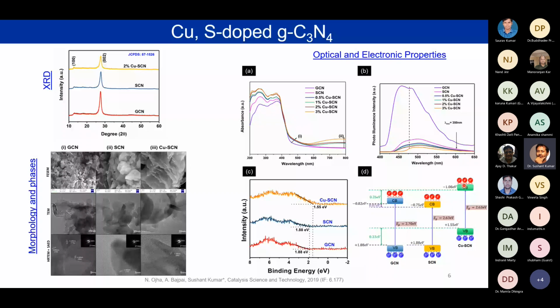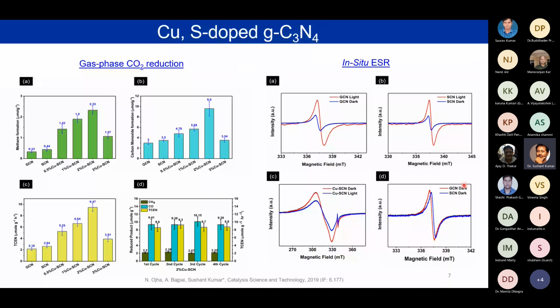Now, in the reactor design that we have, we have seen that methane and carbon monoxide have both formed, and these are the product formation rates. Here you see that the 2% copper SCN has given us the highest amount of methane, and likewise it has also given carbon monoxide. Now we look at the total consumed electron number, and we have seen that yes, 2% copper SCN has given us more. Now we looked at the stability of these results. We have conducted the experiments for more than 5 cycles, and here we are showing only 4.